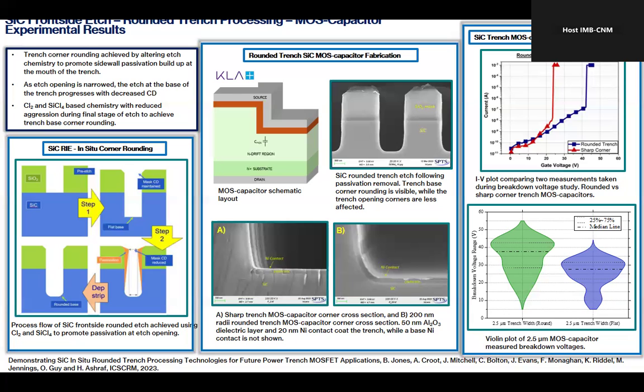And you can see on the top right-hand side of the slide the difference that made. All we did was make MOS capacitors and check the breakdown voltage, and you can see it's about a 50% difference. This is the rounded trench versus the sharp corner. So you can see how important the processing of the trench is for relieving long-term reliability effects on trench power MOSFET in silicon carbide. Rounded corners with high radius of curvature are vital, because you're potentially reducing the lifetime of the part by years if you don't adhere to these kinds of process rules.